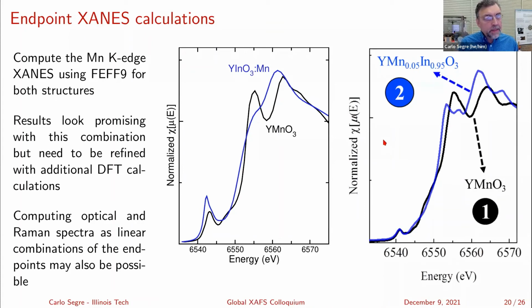Wien2K presumably does XANES calculations. I have not gotten it to work as well as FEFF. I'm not satisfied with what you get. Maybe because the energy is a little bit high on this, it may do better on the very low energy edges. Like, for example, the L edge of manganese, it might be better with that. But I was not satisfied with the way Wien2K worked out.